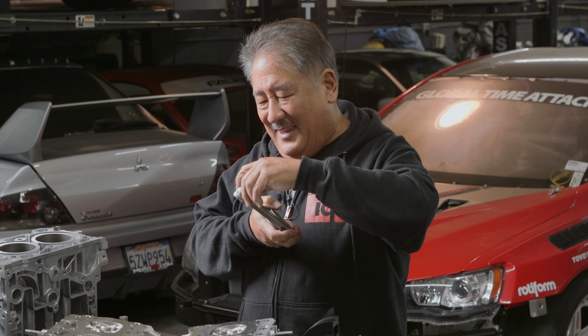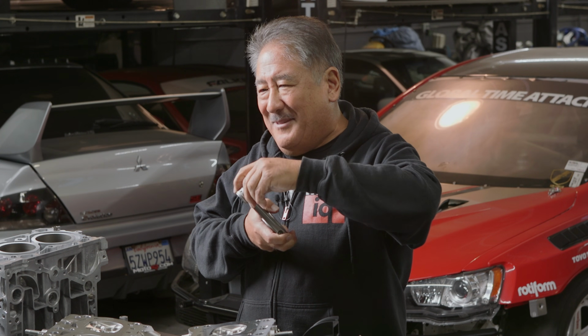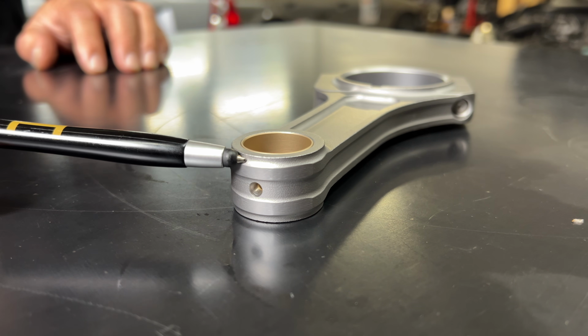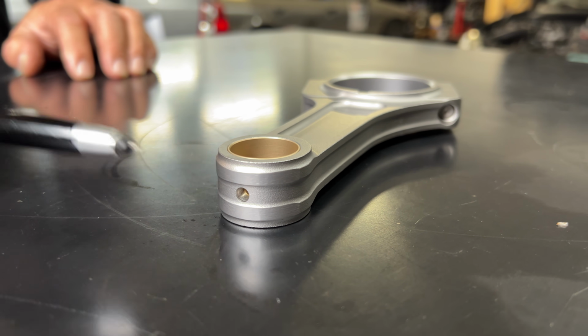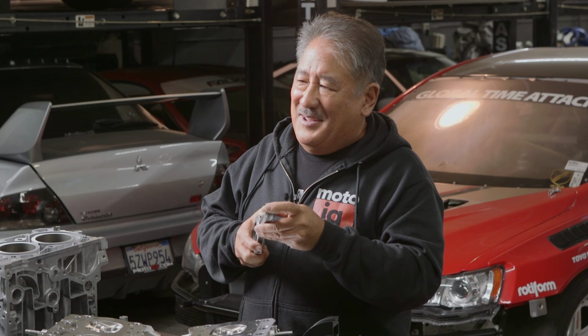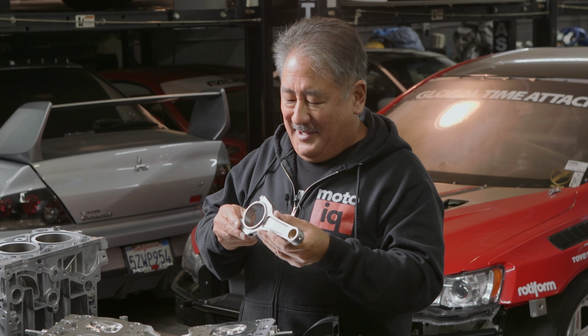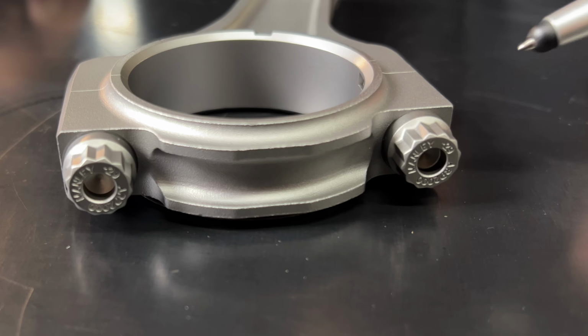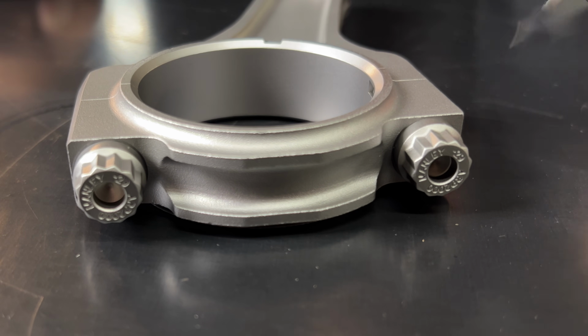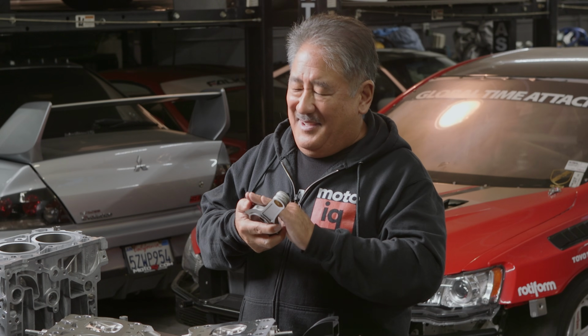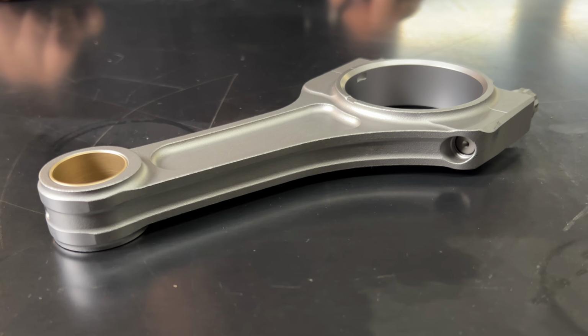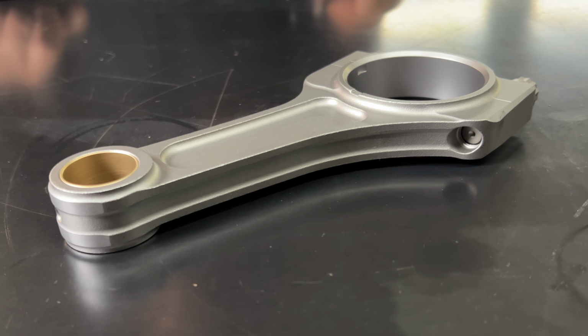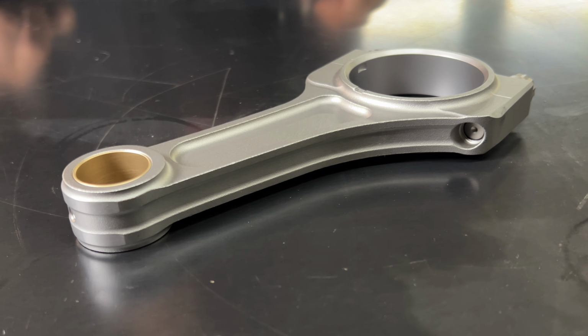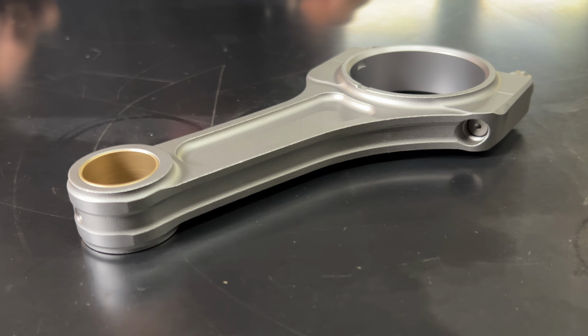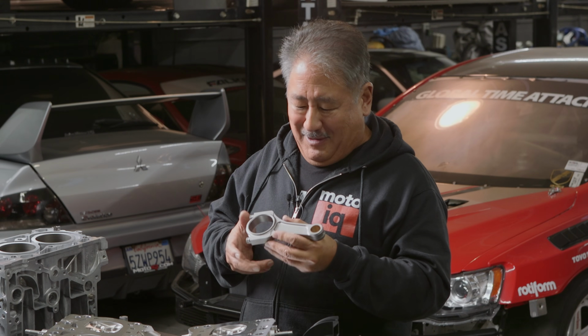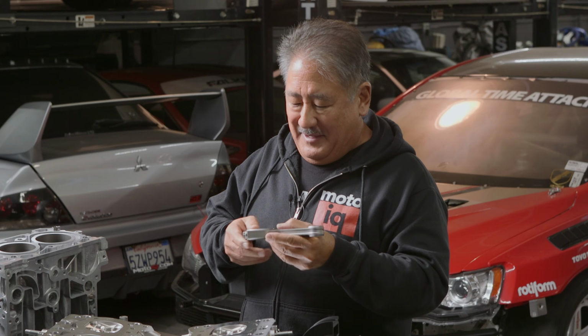Like one of them is the ribs across the small end of the rod. This really increases the strength of the small end, and the small end is probably the second highest stress part of the rod. It has ARP 2000 bolts, and the whole rod is shot peened. Shot peening also increases the fatigue strength by 100% to 200%. It's a fairly aggressive shot peening, so I think it probably makes a pretty big difference.